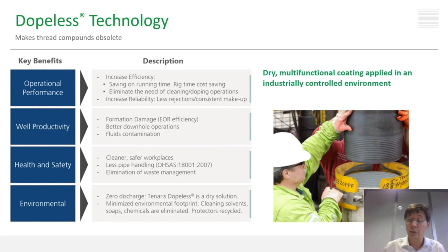This coating will completely eliminate the need of applying storage dope, removing storage dope, and applying running dope, bringing significant improvement to the operations by increasing the efficiency, saving running time, and reducing the activities on the rig itself. Dopeless will also avoid any discharge into the fluids or into the formation, hence avoiding potential damage to the formation, maintaining an optimum productivity for the well.